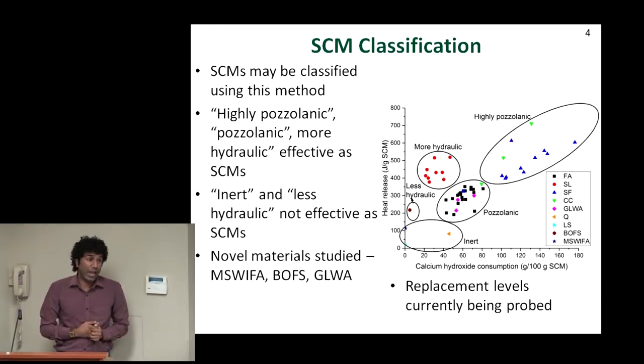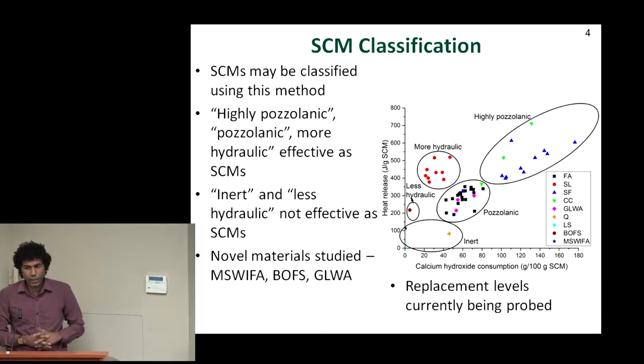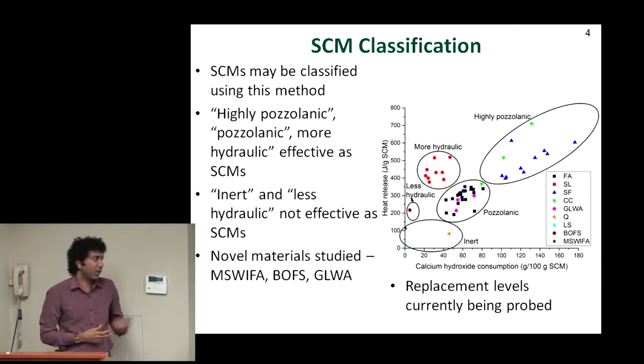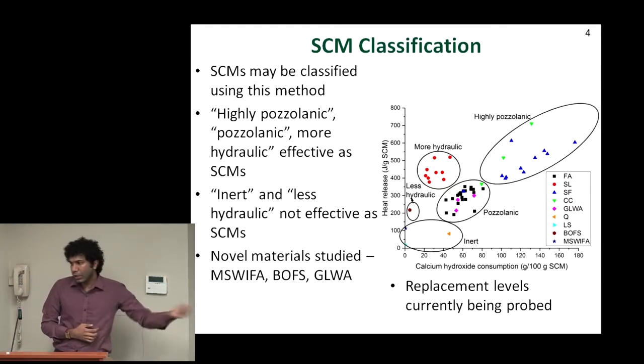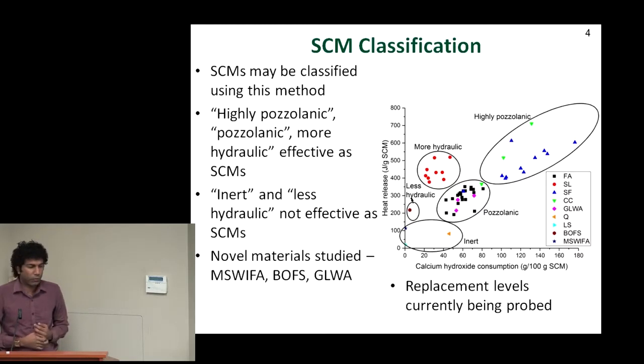The other is a slag coming from the iron making industry. Both of these materials are from China. Unfortunately, they're really new materials, but they turn out to be not very useful. The third is a powder coming from grinding of lightweight aggregates, which is used very commonly in concrete. That one actually turns out to be pretty good.